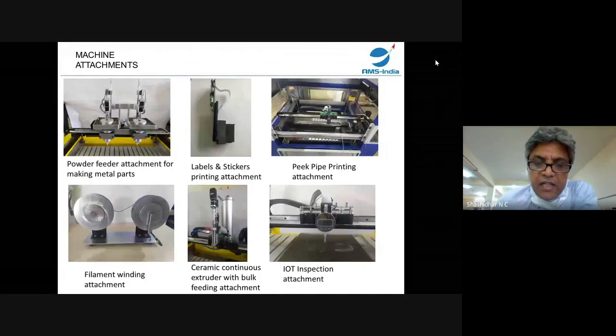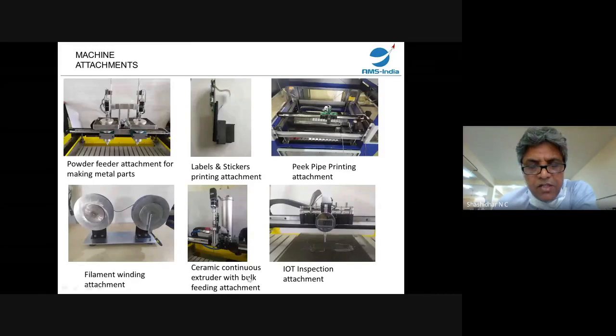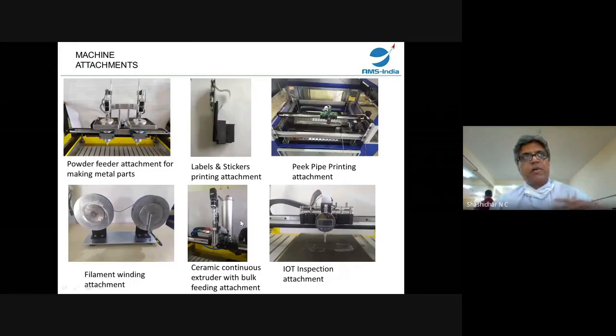We have a continuous ceramic extruder with bulk feeding attachment, so you'll be able to print bigger parts. Like for DRDO, we are printing a very huge rocket cone, like a bomb cone. It's nearly 500 millimeters in height. So this ceramic, once they fit it to the front of the bomb, when the bomb is ejected out and it falls, there's a pin which actually has to squeeze and then the bomb will burst. But here we are trying to make it out of ceramic, so when it drops, it is sure that it's going to break. This is the fundamental of how it makes the machine more powerful for printing ceramics.